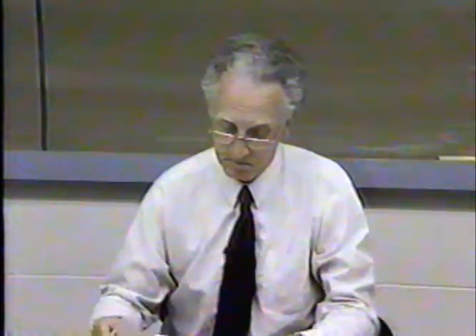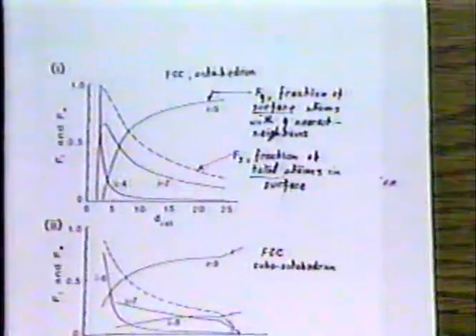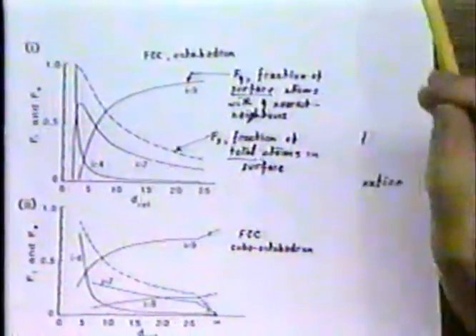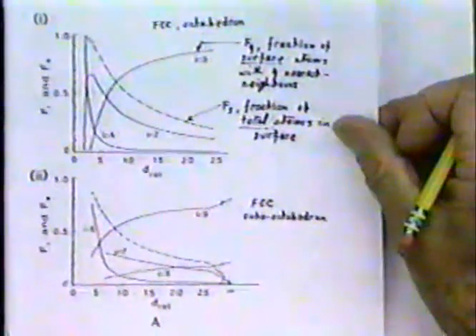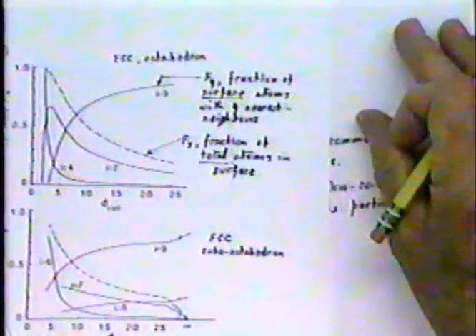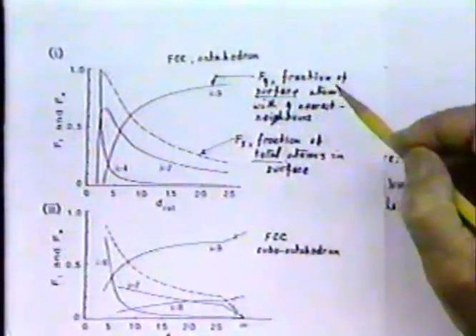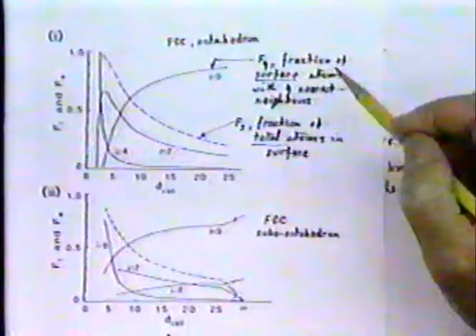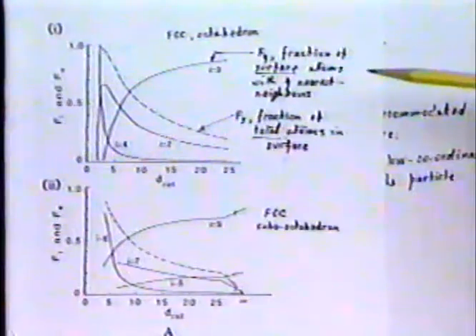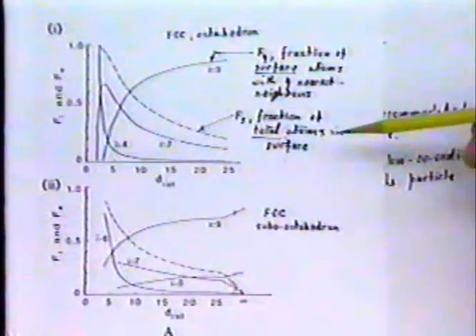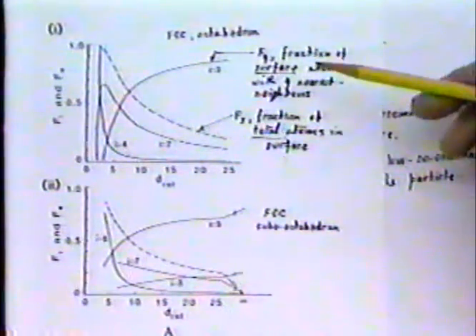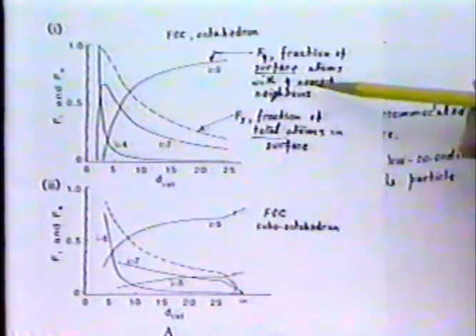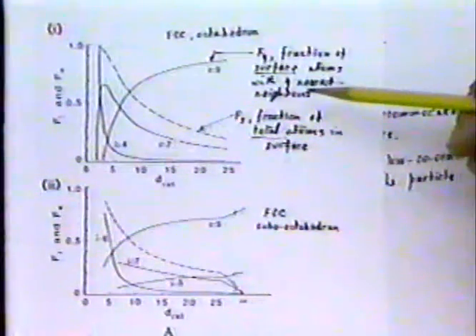Let me now go back, and I'm sorry to jump around like this, and have a quick look at diagrams 8 and 9. Diagram 8 looks a bit of a mess. It's taken out of the structure of metallic catalysts, where there's an atlas of these things. All it does is to give you some idea of the fact that both the fraction of total atoms in a crystal which are present in the surface, and the fraction of atoms with given numbers of nearest neighbours is strongly dependent on the crystal size.